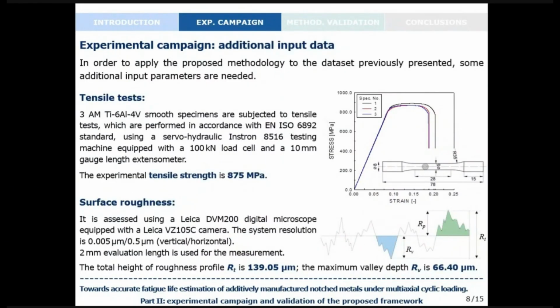Then, in order to apply the analytical methodology proposed, some additional input data are needed. So we performed tensile tests on 3 smooth specimens. You can see the geometry of the specimen here and the stress strain curves obtained in this graph. And the experimental tensile strength obtained is 875 megapascal. Then we analyzed the surface roughness by means of a Leica system with a 2 millimeters evaluation length used for the measurement. We obtained a total height of the roughness profile Rt equal to about 130 microns, and the maximum valley depth value equal to about 66 microns.